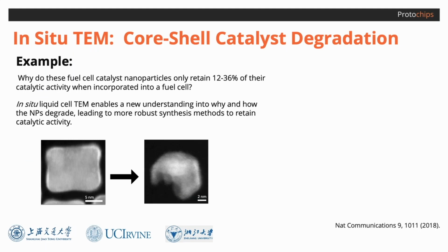In this example, in situ TEM was used to study the degradation mechanism of a core shell platinum-palladium nanocatalyst particle. These nanoparticles show very promising catalytic activity, but when integrated into fuel cells, retain only 12 to 36% of their activity. Conventional TEM imaging of these particles pre- and post-experiment shows structural degradation and loss of surface area, which may be attributable to the loss of activity.